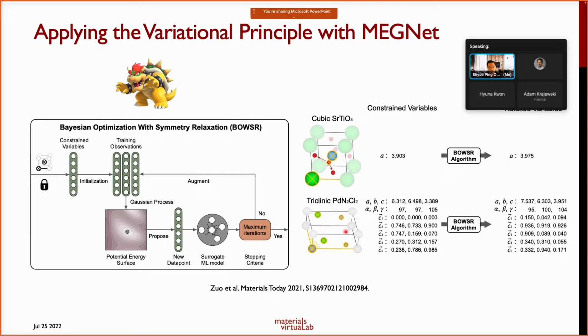If you have a triclinic, because you actually have much lower symmetry, you have 6 lattice parameters and all the atomic positions, and the BOWSR algorithm will just relax everything, right? Okay.